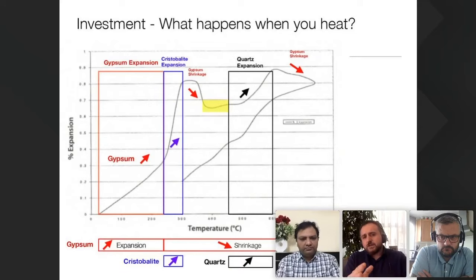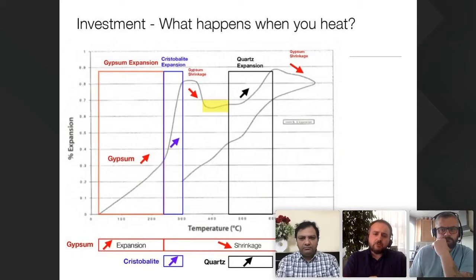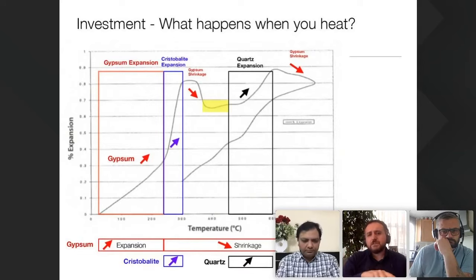And then you continue, you still have towards the end a gypsum shrinkage, around 700 degrees. And when you stop and lower your temperature to cast, the whole investment shrinks back. So this is why the curve comes back down.